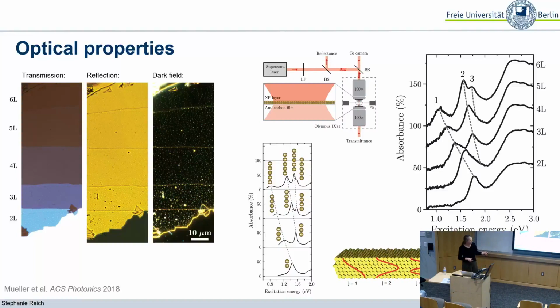And in fact, the entire thing is just an open cavity boundary condition where you get standing waves whenever an electromagnetic field is able to enter, with a maximum of the field strength at the interface, and also able to leave, again with a maximum field strength at the interface. And here are experiments where you can see a very similar behavior. For the bilayer, you have a single excitation, then you have 2 peaks, and they move in energy because you make the crystal thicker and thinner. So the wavelengths that are compatible with the boundary conditions will change slightly.